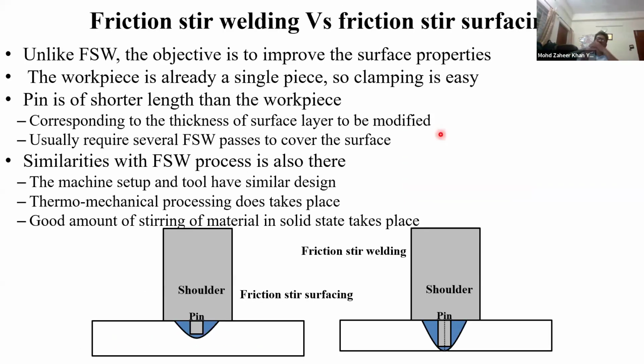So friction stir welding and friction stir surfacing or friction stir cladding are not much different. Everything is the same. The machine is the same, the tool is the same. The only difference is that the pin is of a shorter length than the thickness of the workpiece. In fact, the length of the pin corresponds to the thickness of the material that has to be affected. And just like in the case of other cladding processes, here several passes of friction stir welding have to be carried out to completely bond the clad material with the substrate surface. The good thing is it's a solid state welding process, so no mixing of the substrate and clad material will take place, and the material that we are depositing will remain relatively pure.